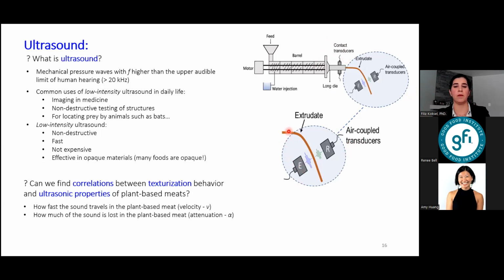So if you magnify it here, the extrudate, the plant-based meat alternative that's leaving the long cooling die, is the one with the dark orange brownish color. And then we have one transducer here that's emitting the ultrasonic wave. And then there's another transducer on the other side of the extrudate that's receiving the signal. And as you can see here, I use a blue and somewhat higher amplitude signal that's being emitted, and then it travels through your plant-based meat alternative, and then it changes its shape. The signal is changed now. It's smaller, maybe it became a little wider, at least in this example. And then this new signal that has been transmitted through the extrudate is now picked up by this second receiving transducer. And then that received signal is sent to a computer for analysis.